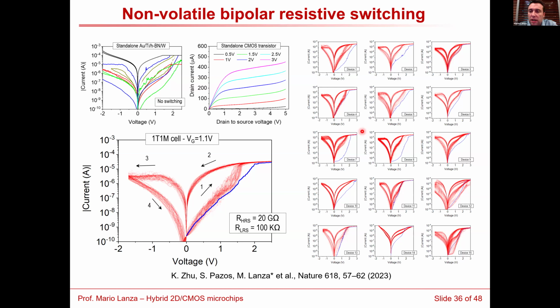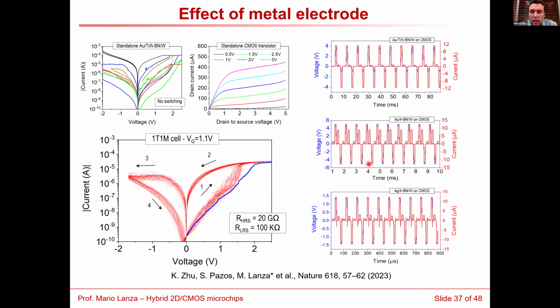Okay, we repeat this in many devices, and you can see that it is reproducible. But the shape of the IV curves is not really perfect in all cases. In some cases, it's much uglier, but in fact, we don't care about this too much because in real applications, the devices are stressed with pulses. So we stress the devices with sequences of pulses like read, write, read, erase, read, write, read, erase, etc. And we measure the current.